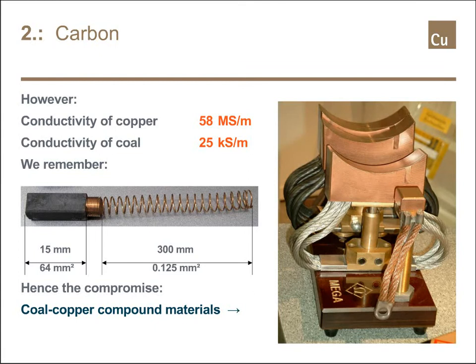You see here that the conductivity of copper is 58 megasiemens per meter, and that of coal is only 25 kilosiemens per meter. This little piece of coal here, which is about 15 millimeters long and 64 square millimeters large, has the same resistance as this spring made of a copper alloy, which is 300 millimeters long and just 1/8 of a square millimeter in cross-section. But still, these two have the same order of magnitude of resistance.